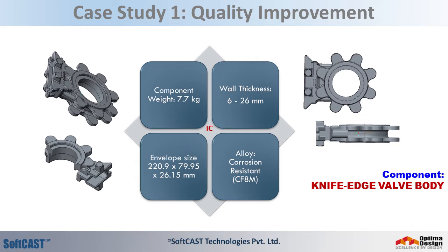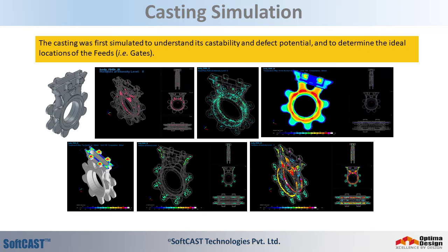Our first case study pertains to the savings from a quality improvement project of a 7.7 kg CF8M knife edge valve body casting. This project was for a medium-sized IC foundry in Western India. The first step was to perform a casting simulation, the results of which, that is hotspots, temperature maps and thermal traces, clearly showed the defect potential, the solidification zones, and the required locations of the feeds, that is, gates.